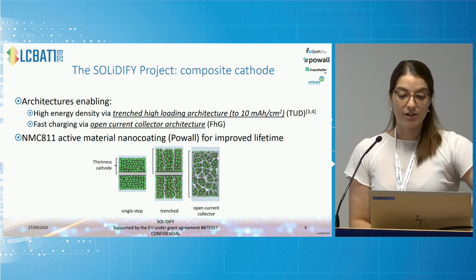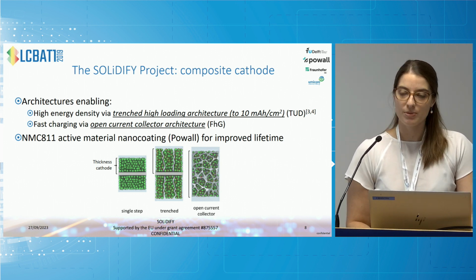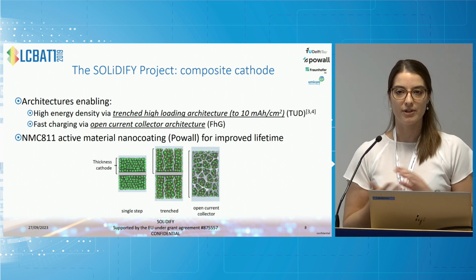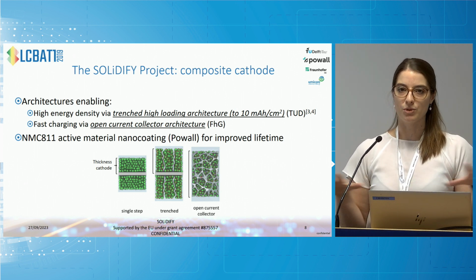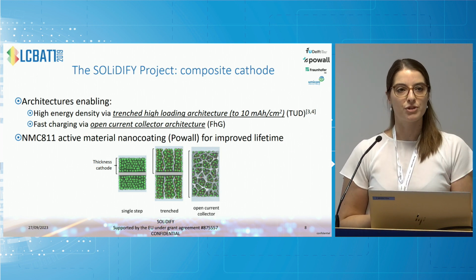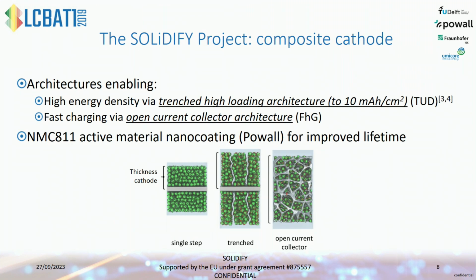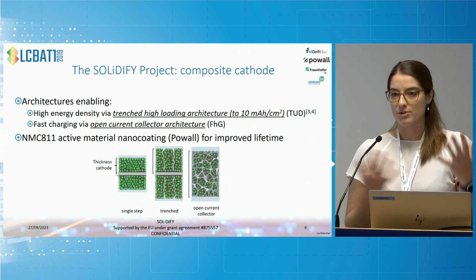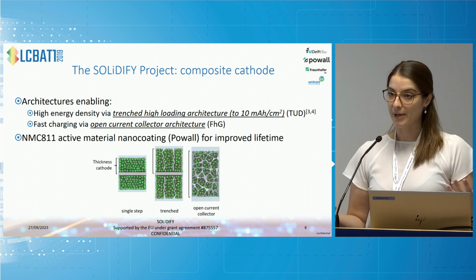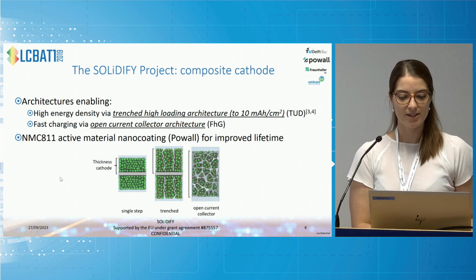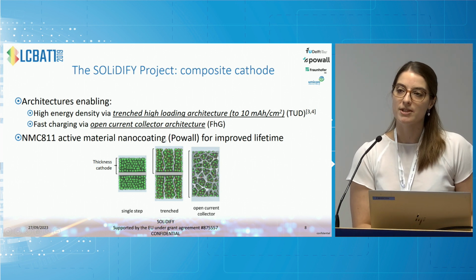With regards to the so-called composite cathode, what we mean here is we have our NMC electrode already prepared, and then we actually infiltrate this electrode with our liquid nano-SE precursor. So that's where the composite side, let's say, comes in. And there are two core aspects of the cathode, one being the architectures. So within the project, we've looked at 3 different architectures, let's say a single-step process or a typical planar process or architecture. We have this trenched architecture, which has been developed by TU Delft.